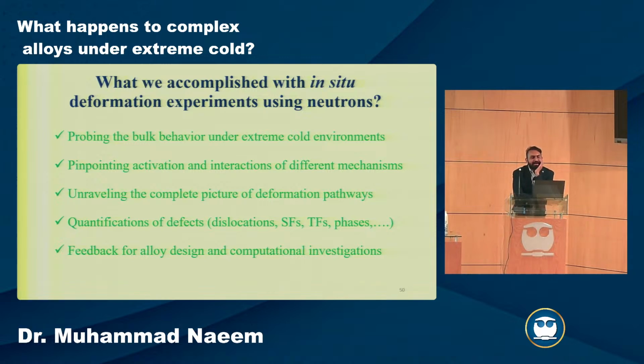Okay, so it's really hard to answer, to be honest. When this paper was published in 2014, they showed that in this alloy at room temperature they had only one deformation mechanism, which is dislocation slip. But when you go to low temperature, you also activate what is called deformation twinning. Because of that, they cooperate, and somehow you can delay, because when you start deforming material, ultimately you have neck formation, right? You form a neck, and then ultimately your material will fracture. So their argument was when you have deformation twinning, you delay this necking instability, which is the instability that ultimately breaks the material.